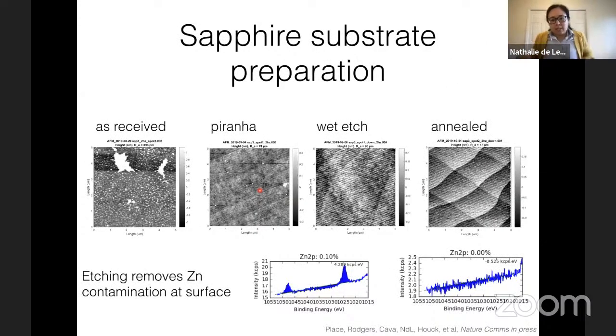Okay, so we set out to tackle these two issues. The first is that it turns out that if you just take an as-received sapphire wafer, which is what they are generally fabricating on, they look absolutely terrible. If you just do standard AFM or X-ray photoelectron spectroscopy, these are really horrible looking, much, much worse than any diamonds that we've ever looked at. So we set out to come up with a way to do sapphire substrate preparation.